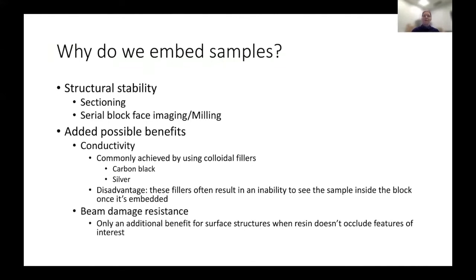So why do we care about embedding samples? Many biological samples do not have the structural stability required for sectioning or milling. So we need to add structural stability to that sample. We do this by, well, okay, we'll get to that in a second, but if we infiltrate a sample with a material, like a resin, we can also infiltrate it with other things that can enhance the conductivity of the sample. We can include things in the resin like carbon black or silver that can help dissipate charging artifacts in the sample. And we can also make that sample not only more structurally stable, but also it can resist beam